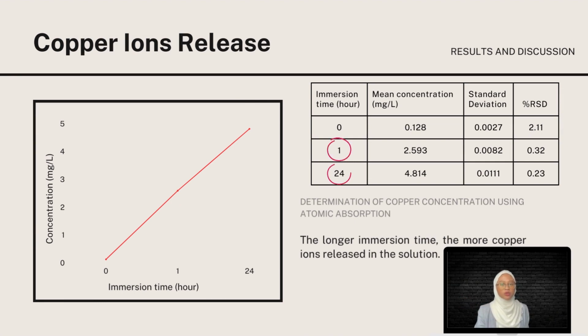For 1 hour and 24 hours of immersion, it again correlated with previous LPR data, as higher corrosion rate released more copper ions, with 2.593 mg per liter and 4.814 mg per liter respectively, while the 0 hour sample solution showed an acceptable result as the short contact time had released considerably few copper ions, which is 0.128 mg per liter.